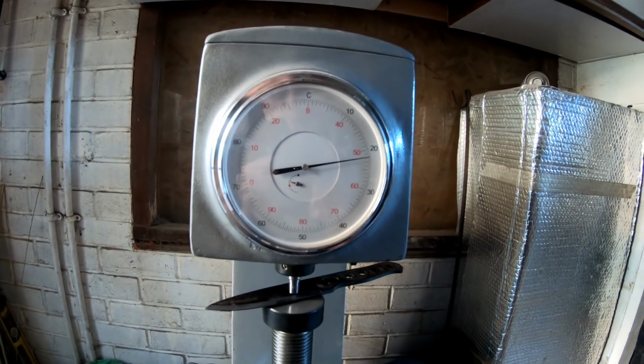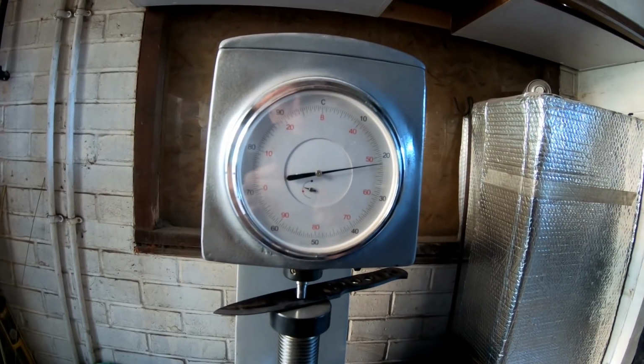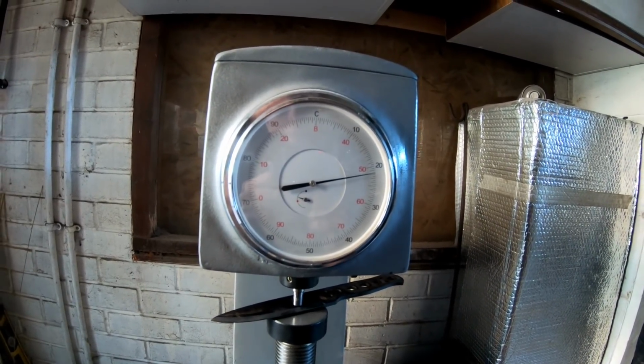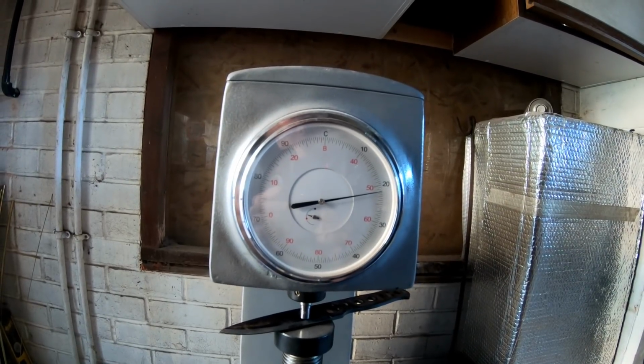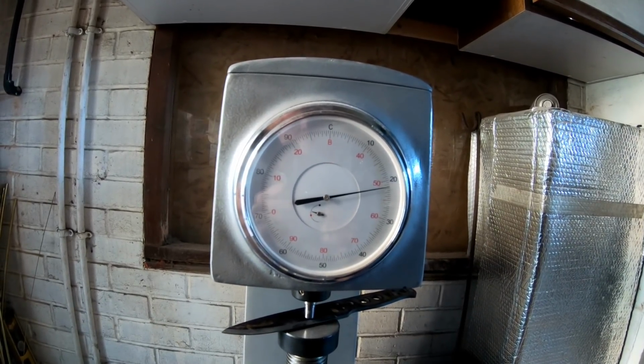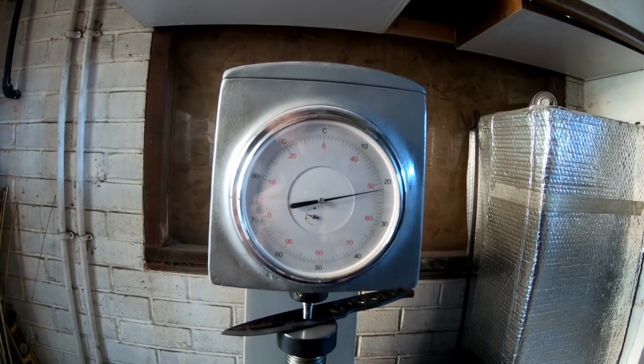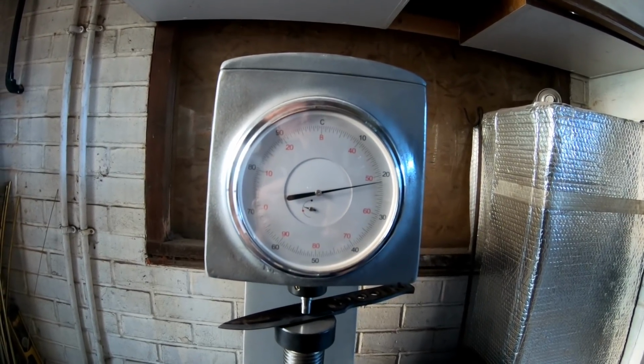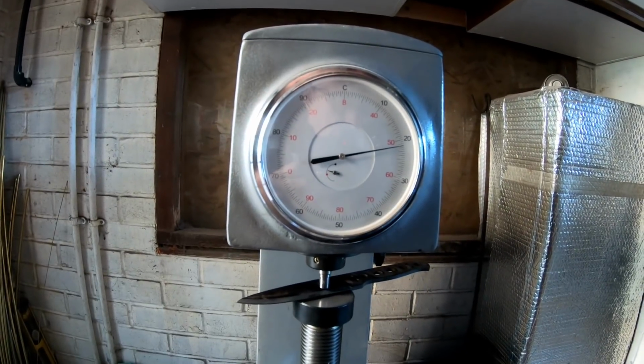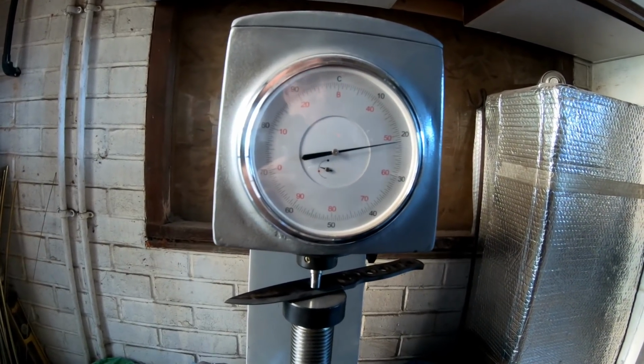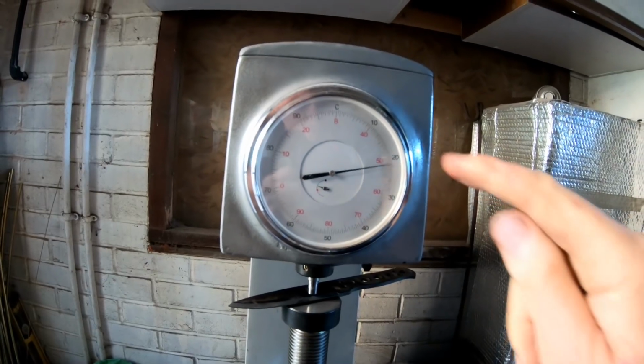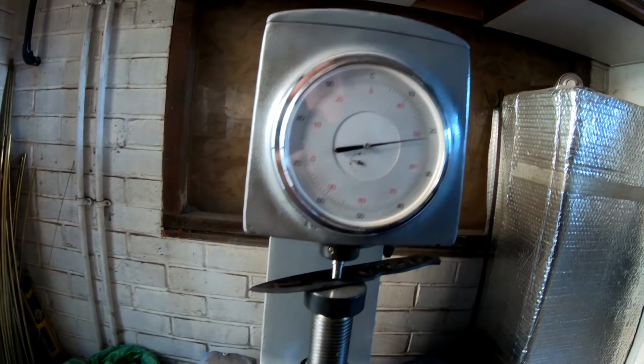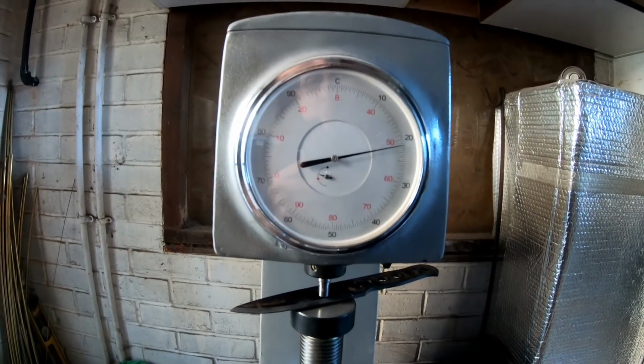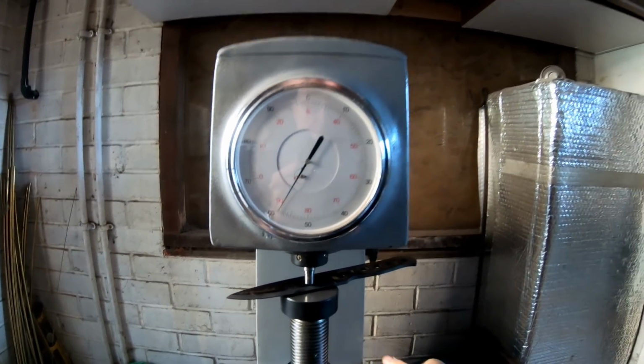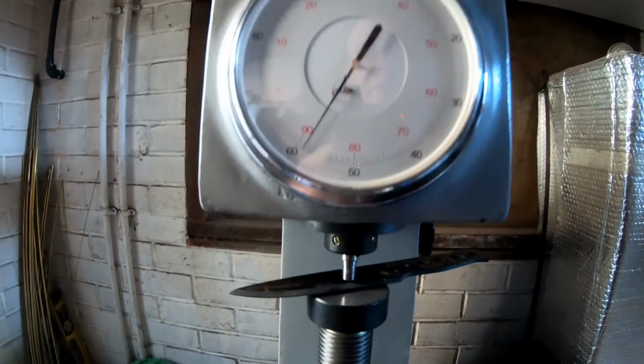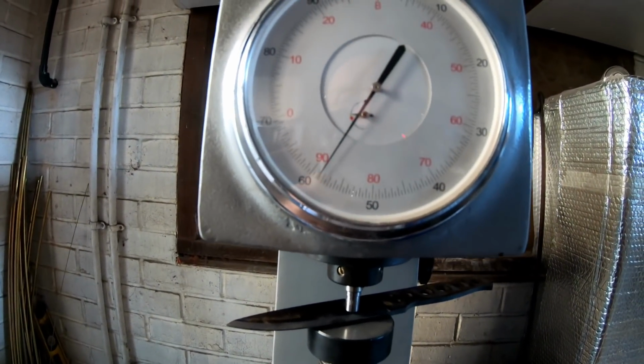The steel is softer. There's a trade-off when you temper steel. You remove some of the hardness. The steel becomes a bit softer, but you also increase the toughness. So I'm looking for that to swing round to somewhere about 59-ish will do. And that's pretty close.